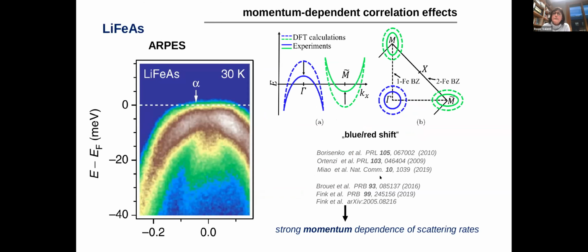However, even though there is a lot of success in these types of calculations, there are features that this conventional way of doing DMFT, what we call the one-site DMFT, is not able to reproduce. The one-site DMFT can describe local correlations exactly, but has no information on non-local correlations. And there is an effect that was already seen a long time ago in some materials of this family of iron-based superconductors, which is called the blue/red shift.